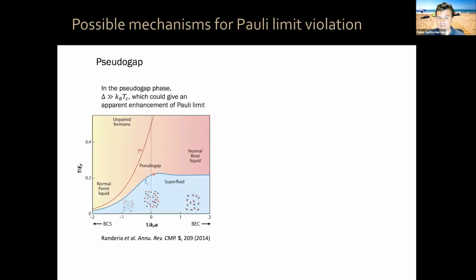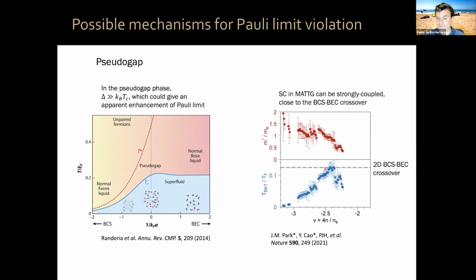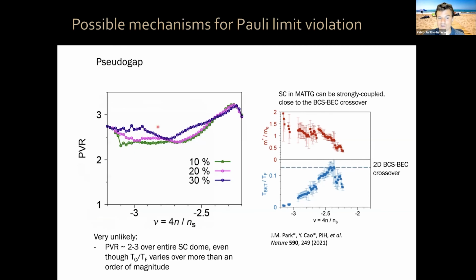Pseudo-gap physics, preformed pairs in the strong coupling regime can also lead to Pauli limit violation, but it turns out that we can vary our coupling strength by an order of magnitude, while the Pauli limit violation ratio is always present, okay? So that means probably this also doesn't explain our Pauli limit violation.